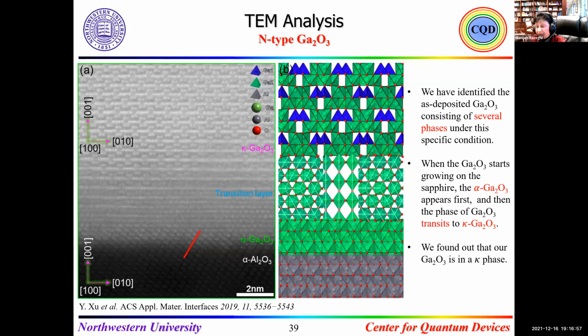And as you know, if you look at the literature, you can see that they try to take the gallium nitride at 2000 degrees under oxygen pressure, and replace nitrogen by oxygen, to have the P-type gallium oxide. So there are differences, but it is rich. So my advice is really, that's the reason I came to this subject exclusively, because it's rich and it's the future.